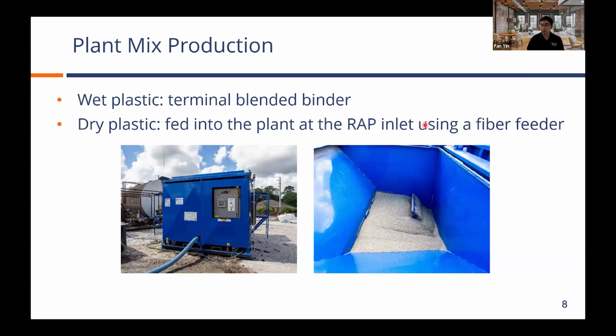For wet plastic, because we are talking about a modified binder system, we worked with our binder supplier to do a terminal blending of that system. So once again, it's not just recycled plastic added into the binder. We introduce the terpolymer and PPA to try to stabilize it and achieve good elasticity from the percent recovery perspective as compared to the SBS. So overall, the production went really well. Definitely want to shout out to our binder supplier and East Alabama Paving for working with us to make it happen.